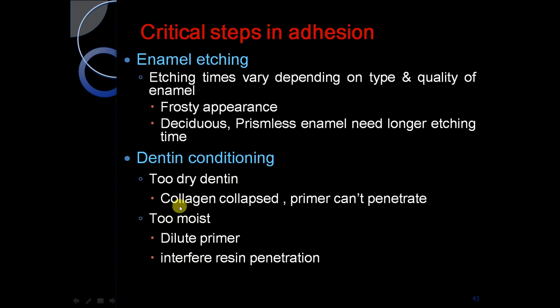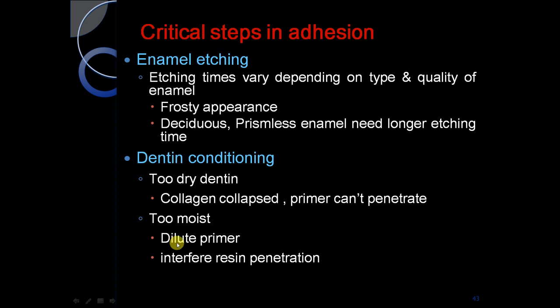Critical steps: enamel etching produces the frosty appearance. In deciduous teeth you get prismless enamel and need to etch for a longer time. For dentine conditioning: if the dentine is too dry, the collagen collapses and the primer can't penetrate. If it is too moist, the dilute primer interferes with resin penetration.